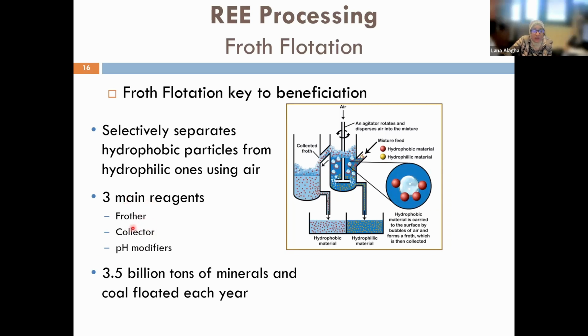And then the frother is added at the end to stabilize the froth, because usually your froth is formed here, and then it will rise. It has to have a specific stability to resist the rupture of bonding between the mineral particles and the air bubbles. So it has to have some stability to be able to rise to the top and then be collected. Stability, of course, and mobility. But too much stability is bad, because you will have more challenges in the consequent separation, especially when it comes to solid liquid separation, when you have the concentrate and you have to separate solid from liquid. So there is an optimum value for froth stability in any process.